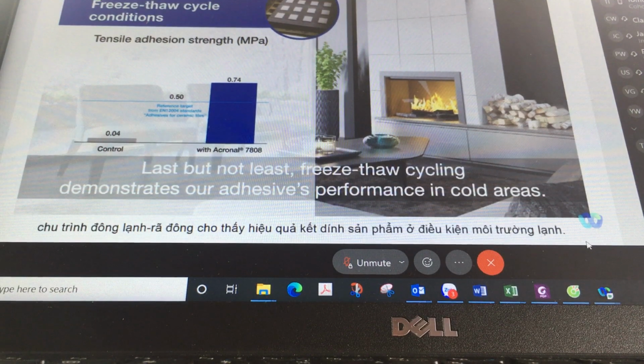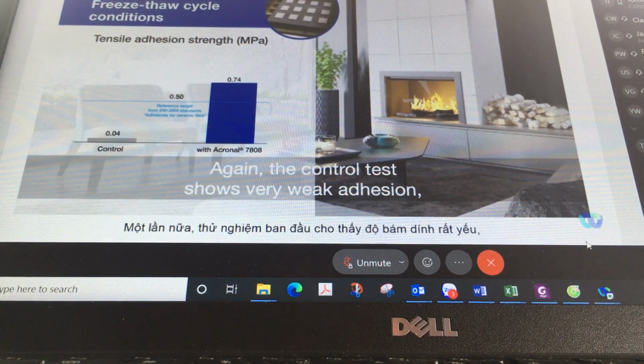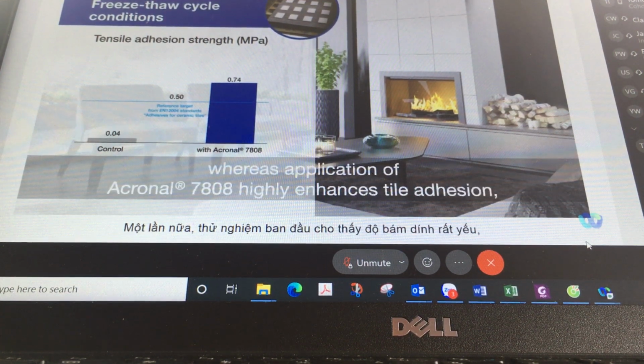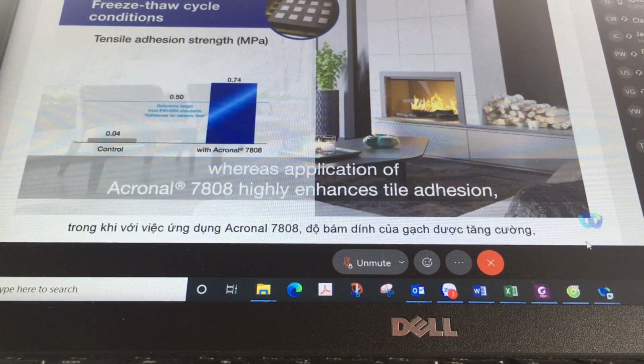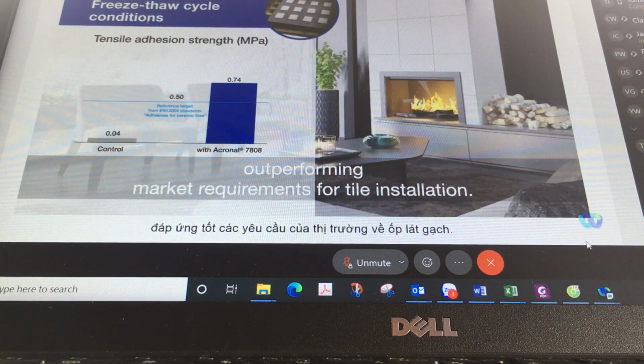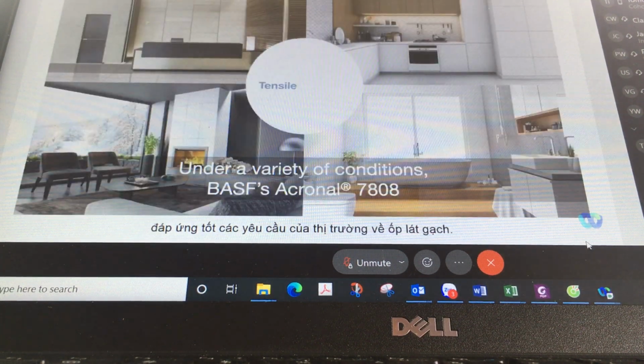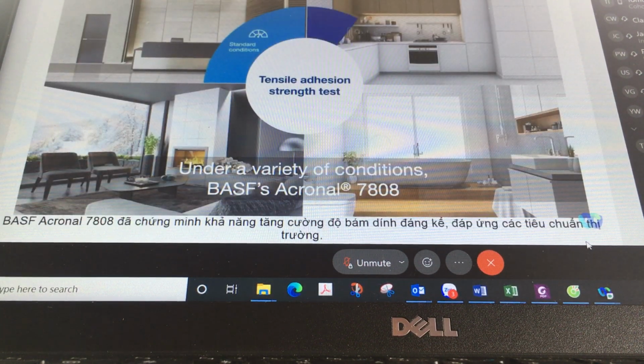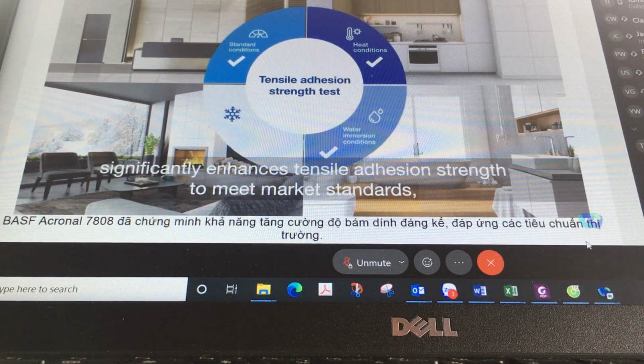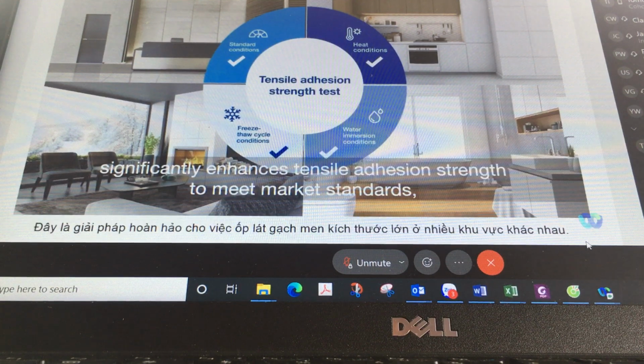Last but not least, freeze-thaw cycling demonstrates our adhesive's performance in cold areas. Again, a control test shows very weak adhesion, whereas application of Acronal 7808 highly enhances tile adhesion, outperforming market requirements for tile installation. Under a variety of conditions, BASF's Acronal 7808 significantly enhances tensile adhesion strength to meet market standards, making it the perfect solution for large porcelain tile installation in various areas.